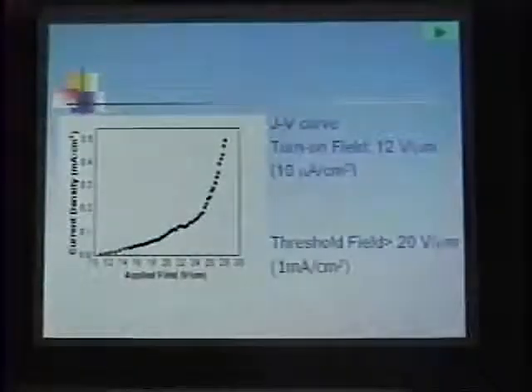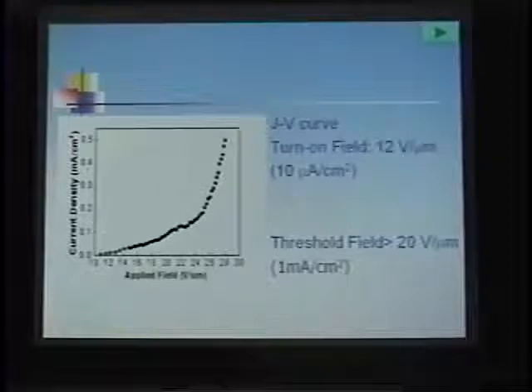For this we also measured the field emission property, and the turn-on field is 12 volts per micrometer. This seems larger than carbon nanotubes, but actually in our case some voltage was applied across the silicon oxide resistance. So this is not the intrinsic property. I'm sure the intrinsic turn-on field will be much smaller than this one. So we are trying to improve the conducting property of the sample.